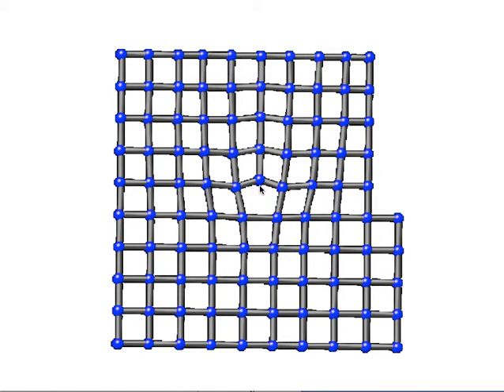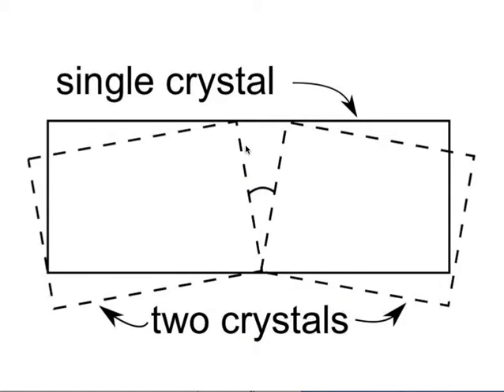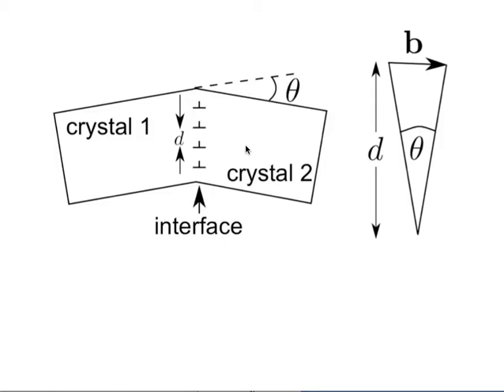So this shows you the structure of an edge dislocation. If you look carefully, these planes here are tilted with respect to each other, okay? And then we have this extra half plane. So if I have a gap like this and I put an array of edge dislocations there, then that would fill up the space, right? The number of dislocations that I have to put in depends on how much of a tilt I put on that crystal. So this is what an interface geometrically would look like.